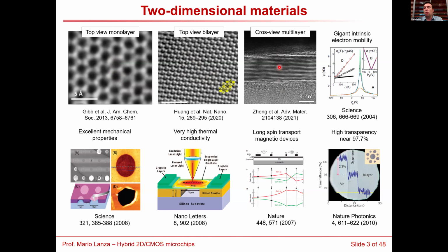Okay, you will see that I work with an insulating two-dimensional material, which is multi-layer hexagonal boron nitride. Because it's insulating, I need multi-layer. Otherwise, if it is only one layer, it's more difficult to apply, because for the insulator, we need to block the electrical current. So if there is only one layer, there is quantum tunneling effect. So normally we work with a little bit thicker materials, and this is how it looks like.